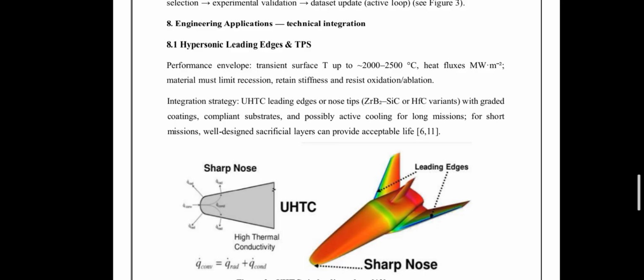So the integration strategies: leading edges and nose tips made from zirconium diboride silicon carbide and hafnium carbide composites. Use of graded coatings to manage the oxidation and thermal expansion, and compliant substrates to reduce the thermal stress. Optional active cooling for extended missions, and sacrificial layers suitable for short duration flights. This figure shows where we use the ultra high temperature ceramics, and the hot red part shows where it can bear the maximum heating temperatures.